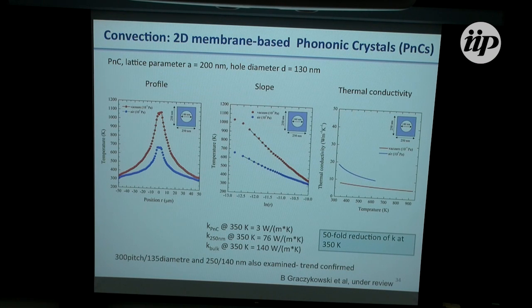By this time, we had also become very aware that we had to measure both in vacuum and in air, to be consistent with the measurements that were done before when we were comparing our measurements to the Virtual Crystal calculation. And so here we have data for one crystal with a periodicity of 200 and holes of 130 nanometers. The profiles in vacuum reach higher temperature because there is no air convection to take heat away. And here is the comparison, red in vacuum, blue in air. So that's temperature versus position.